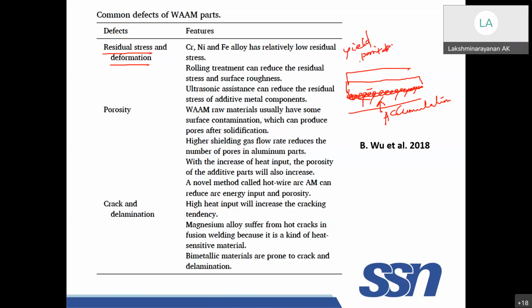If the residual stress built within the material exceeds the yield point, the material will undergo deformation. Suppose I want to have a shape like this, but unfortunately, because of the residual stress, I will end up with this kind of deformed structure. So to avoid that, usually they do rolling treatment. I have a video for you. After a pass, they will do rolling, which will induce compressive residual stress. See, there is the residual stress.